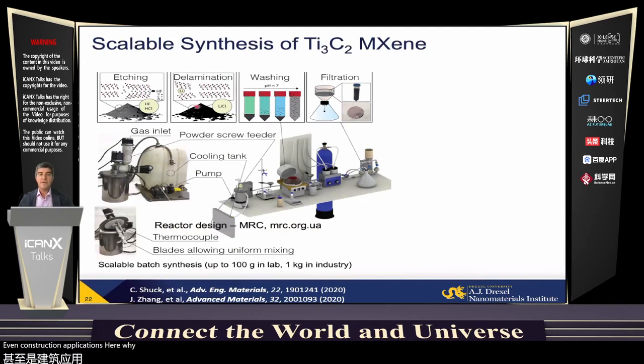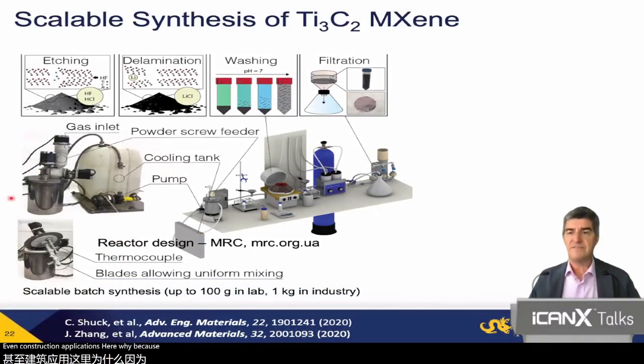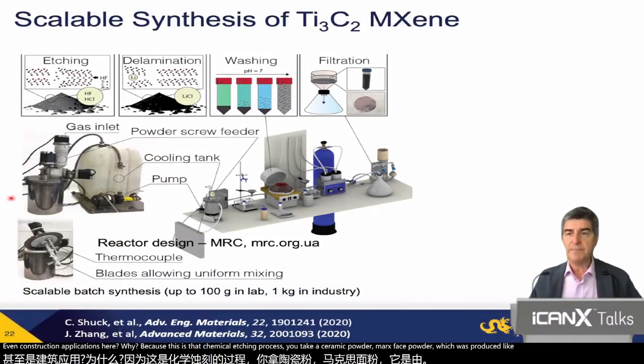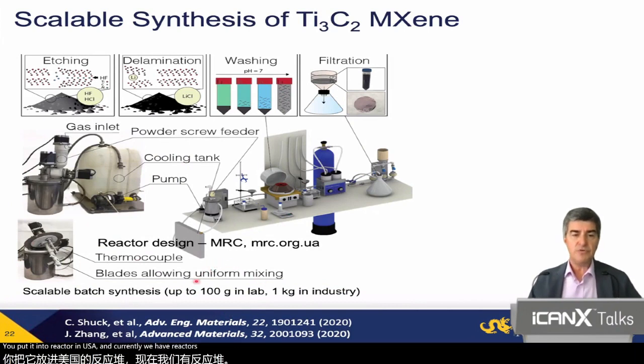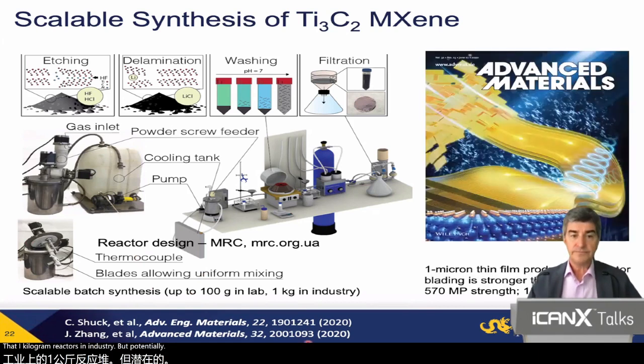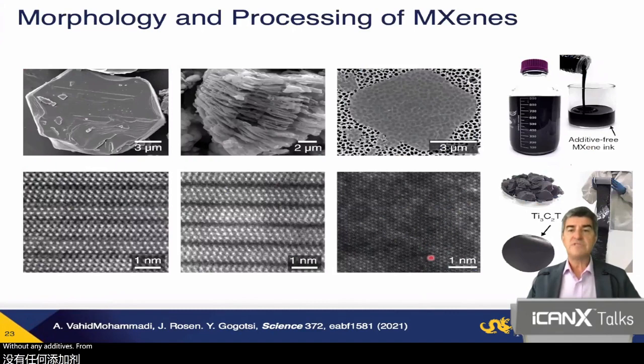Why? Because this is a wet chemical etching process. You take a ceramic powder, MAX phase powder, which was produced like a high temperature ceramic by conventional technology. You put it into a reactor and you etch it. And currently we have reactors producing up to 100 gram. There are kilogram reactors in industry, but potentially it can be 100 kilogram, 1 ton reactor here. What do you end up with? You end up with a powder here. And actually, you can process it into films, into structures, without any additives from aqueous solutions.